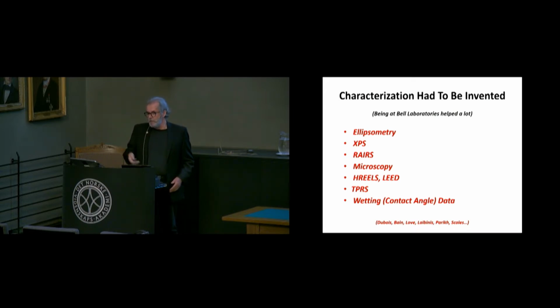So, for example, the incomplete list of items in this recipe were things like ellipsometry, XPS, reflection absorption infrared spectroscopy, microscopies, X-ray methods, for example, to characterize the crystallographic textures of the substrates that were actually present, because when you evaporate a gold film, do you actually know what the crystalline form of it is? So there's a lot of things that you figure out, and there's other things shown on here. For example, low energy electron diffraction, which provided an important early lead as to the characteristic order present in these systems. And of course, because they were easy to do, we always measured wetting and contact angle data.